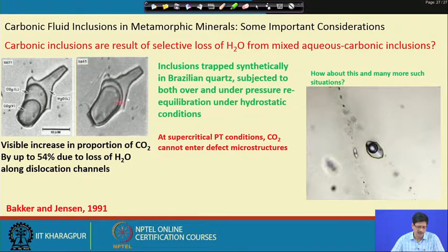The authors of the work, the people who conducted it, examined the host quartz crystal with the help of a transmission electron microscope and a scanning electron microscope. They observed that in the surroundings of these trapped inclusions there are some dislocation planes and crystal defects, which could be traced out with the help of the transmission electron microscope.